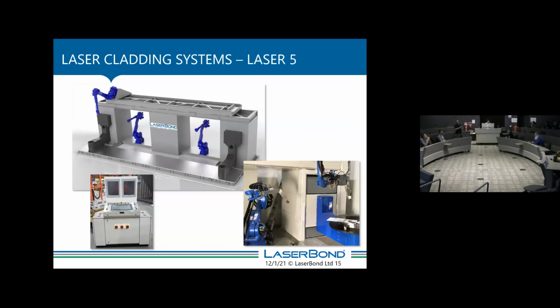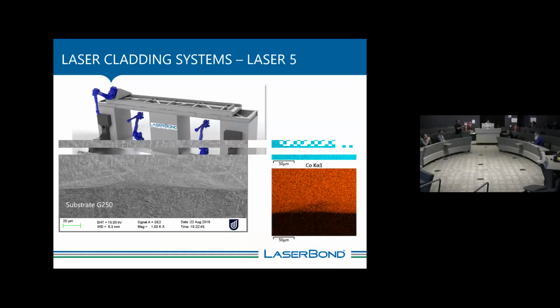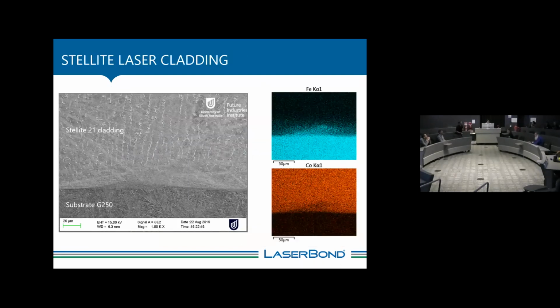Version that's on laser 5 we have installed here in Additive. Picture the parts, just a quick cross-section for the laser cladding. Remember I mentioned that we talk about dimension, wide penetration, just giving an impression. We see Stellite 21 cobalt and a cladding of cobalt-chromium-molybdenum on a G250 substrate, so it's mild steel. And this is the interface.